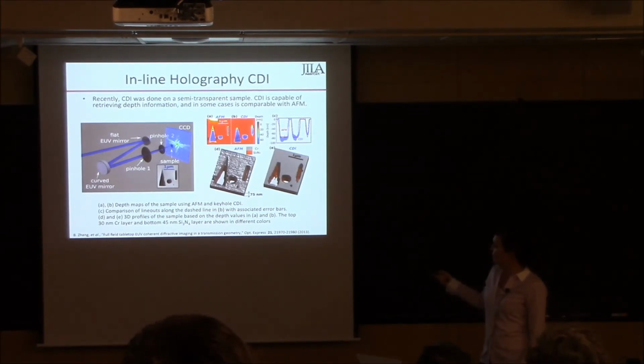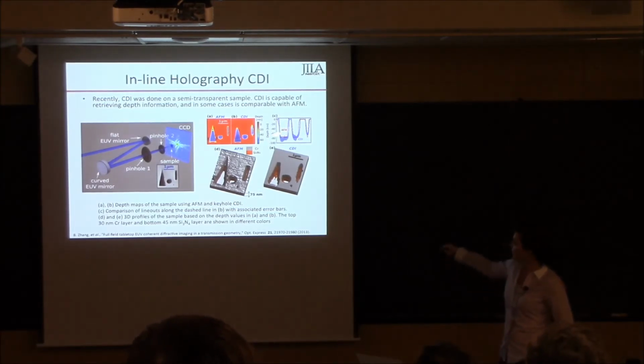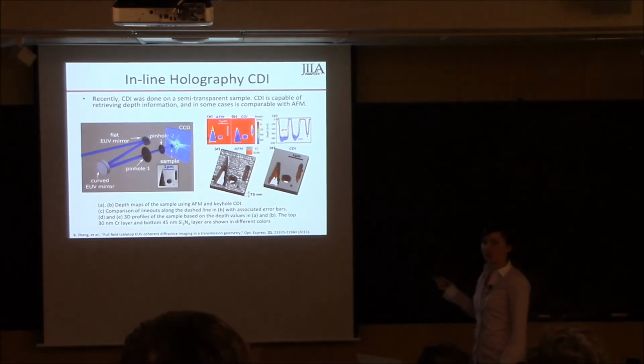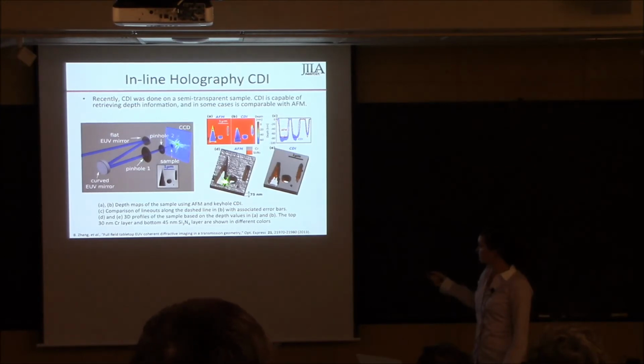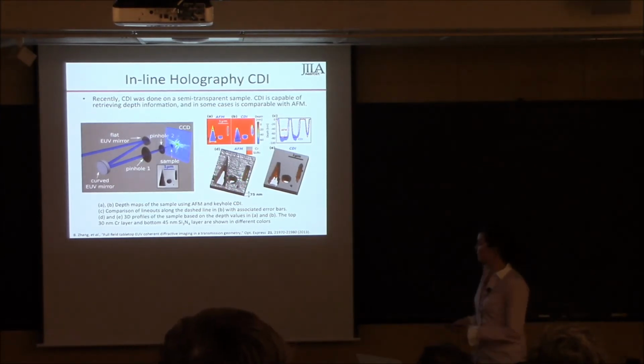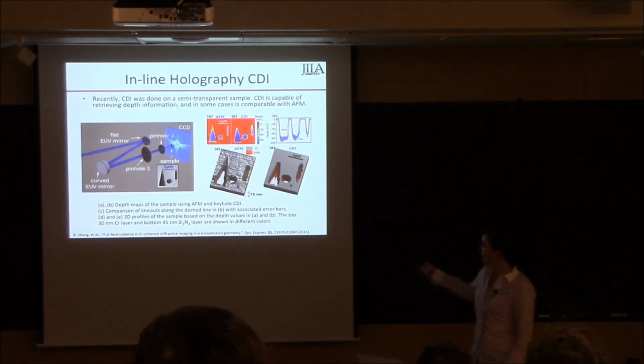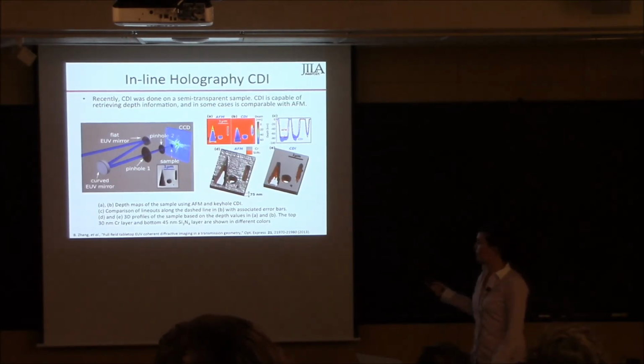So here you can see an AFM image of the sample showing the depths as well as a CDI image, and then a line out that's taken across the sample. And you can see that AFM and CDI agree pretty well within their error bars. And then down here are 3D profiles of the sample based on the depth values. And these two colors are just showing that it's 30 nanometers of chromium on top of 45 nanometers of silicon nitride.